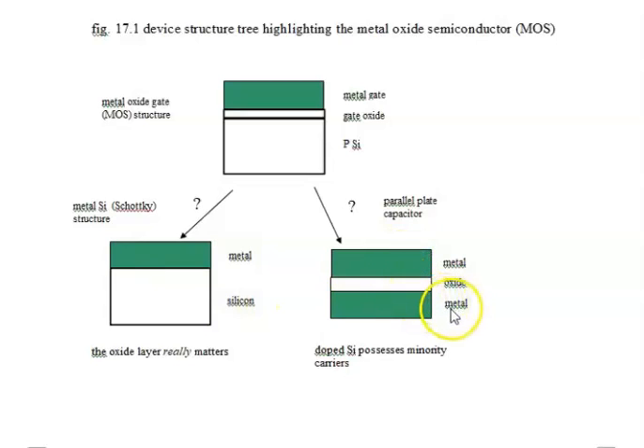Well, how about the parallel plate capacitor? In a parallel plate capacitor, we have a metal for the bottom electrode rather than silicon. Well, one can argue that if we have heavily doped or even moderately doped p-silicon, this is a fairly good conductor. The problem is that in a parallel plate capacitor, when we apply a bias between the two metals, it doesn't matter what the sense of that bias is. We could apply minus to the top metal, or we could apply a positive bias to the top metal. The capacitance is only a function of the structure. In an MOS type structure with p-silicon, if we apply a negative bias to the top metal, we're going to attract holes. Minus up here will attract holes, and that will be pretty much like a parallel plate capacitor, minus on the top electrode and positive on the bottom electrode.